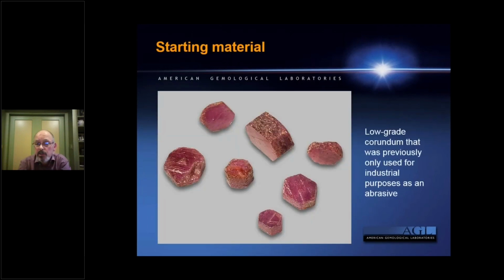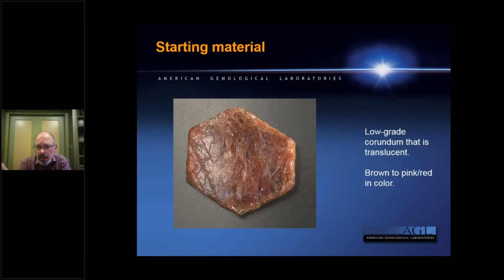The starting material is this very low-grade corundum, which previously had no use in our industry. It was mainly used for industrial purposes as an abrasive. You can see this kind of material here, different colors of this material. It's a multi-step process. The first step of this treatment process is an acid treatment to leach out and clean up the structure, to remove all of these foreign mineralizations and to open up the structure. And then in that state, the stones are not actually stable any longer. They're quite fragile, you can even break some of them apart by hand.